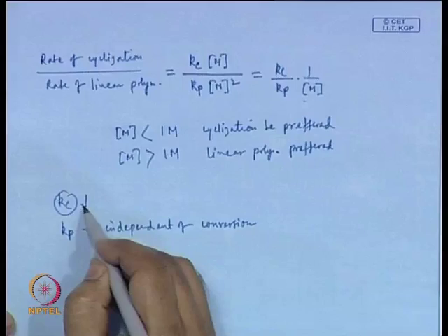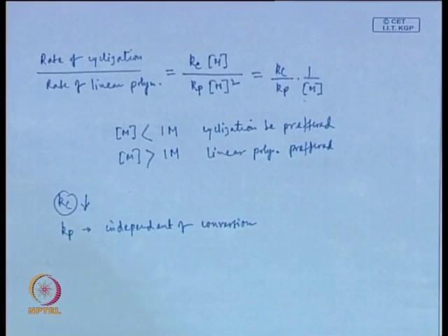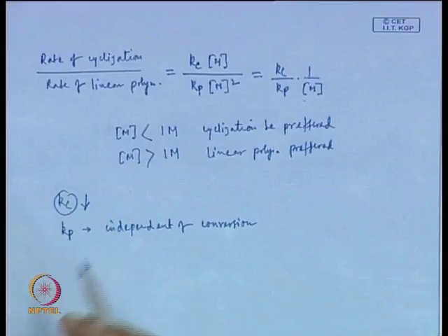As the chain grows, the kinetic feasibility of the two functional groups present at the ends coming together and reacting to form a ring comes down, which means that Kc comes down as the reaction progresses, because the longer the chain, the chances that two ends will come and react in an intramolecular reaction, forming a ring, is always lower. So, as P progresses, Kc comes down.